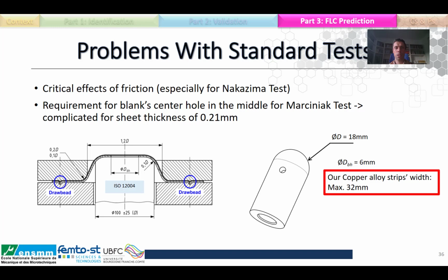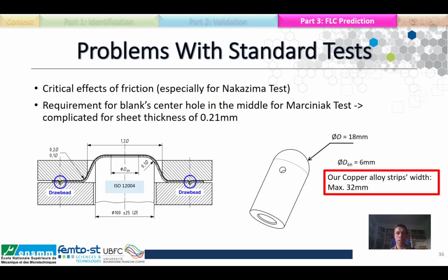When miniaturizing the standard test to our scale, we were facing some difficulties with the tests proposed. For example, the importance of friction is greater in microscale, especially for Nakazima tests. And to perform a Marciniak test experimentally, the difficulty is to achieve the blank sub-thickness size that corresponds to our strip thickness. That's why we chose to use the Marciniak test for simulation, because we don't have the problem of manufacturing the sheet. But for the experimental test, we use Nakazima.